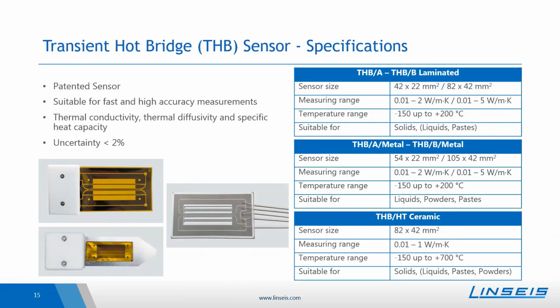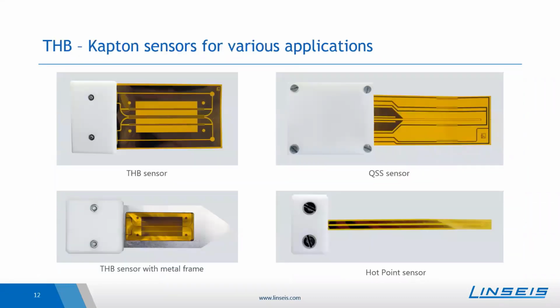A further question is which sensor is recommended for construction steels? This can be easily answered. This is the QSS sensor. The THB sensors can measure only up to about 5 watt per meter Kelvin, and the QSS sensor is especially suited for the higher conductive samples. The hot point sensor is more useful for very low sample amounts, and it's more used for comparative measurements.